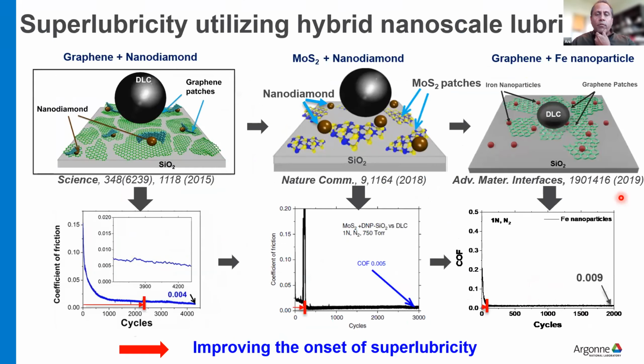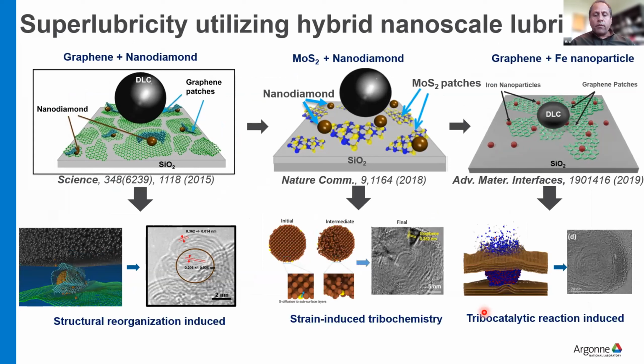So over the years, we developed different kinds of lubricants. As I said, we see a very interesting behavior in the run-in. The time to reach superlubricity is about thousands of cycles. But when we switch to MoS2 and nanodiamond, it drops to a few hundred cycles. And when we switch to graphene and iron nanoparticles, the run-in period goes to a few tens of cycles. So the time to get superlubricity is reduced substantially, and there is a very interesting mechanism at play at these nanoscale contacts.